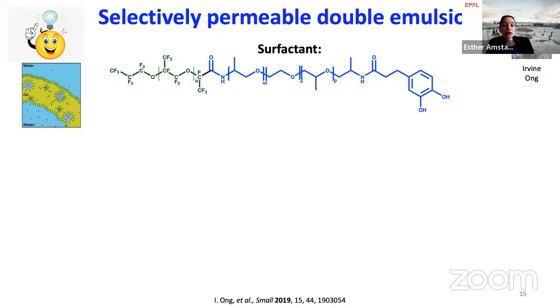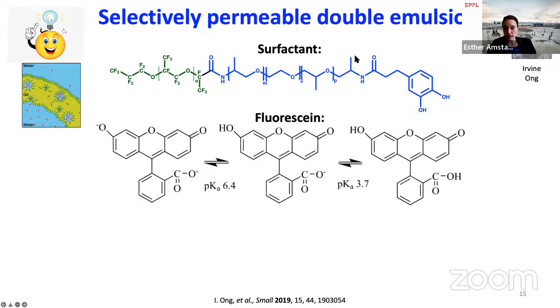So there again, we took inspiration from nature, from the mussel byssus, but this time from the adhesive properties of these mussels, which comes from a molecule called catechol, which looks like that, very strongly binds to certain ions, such as iron. And we thought, well, maybe we could use this molecule to reversibly bind our surfactants at the interface of the drop. So we synthesized these functionalized surfactants, and we stabilized the emulsions with them.